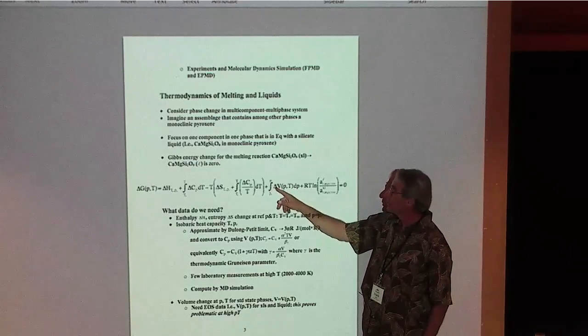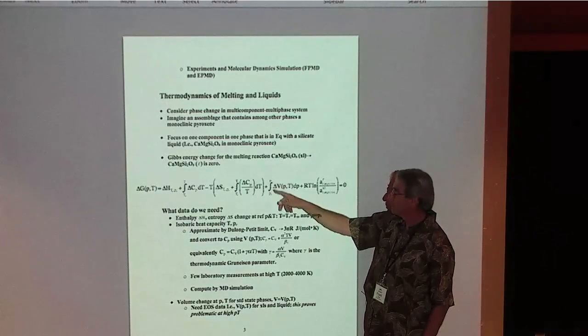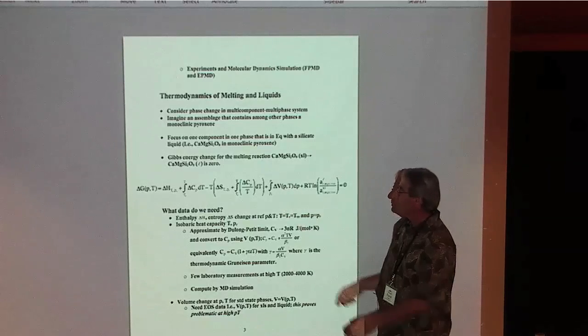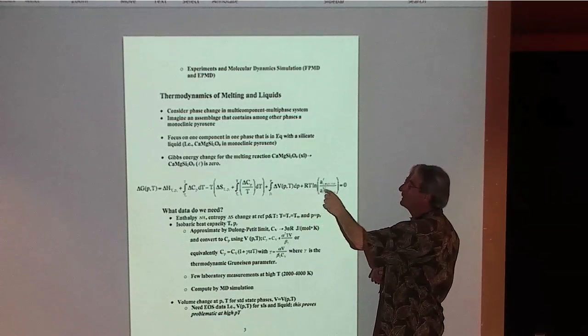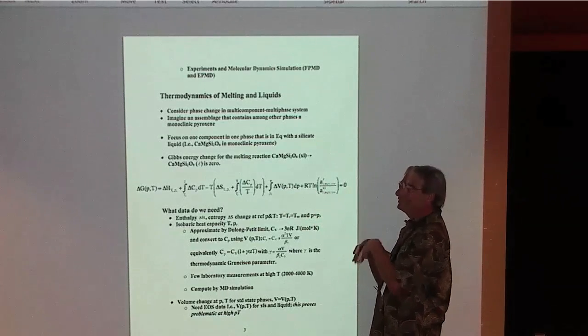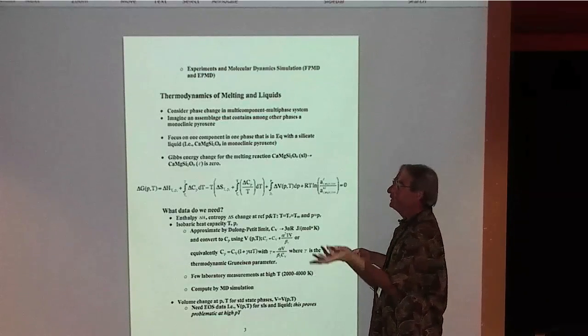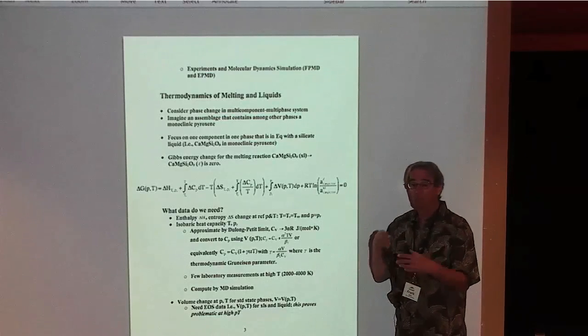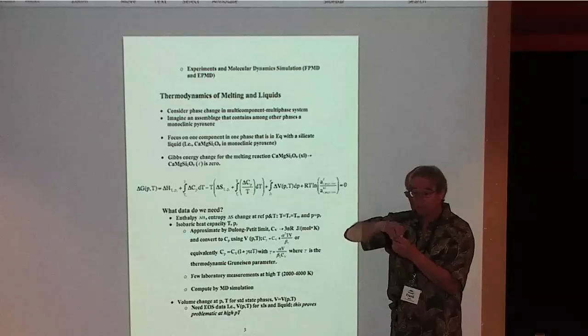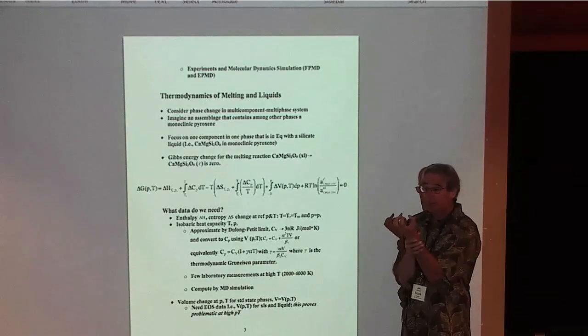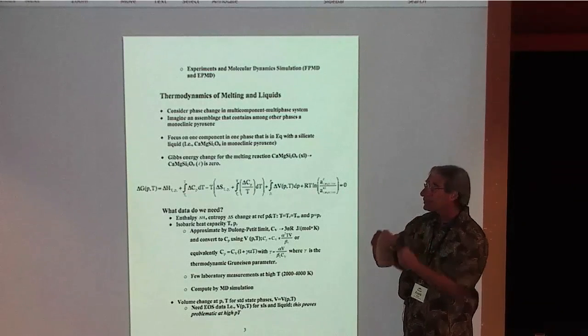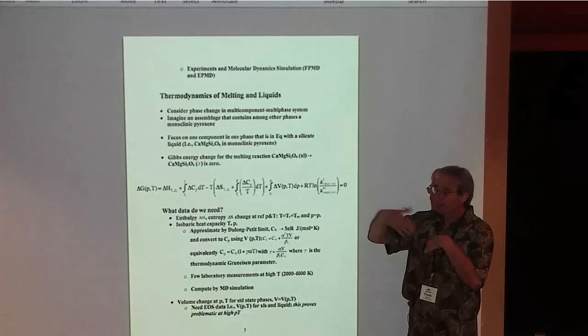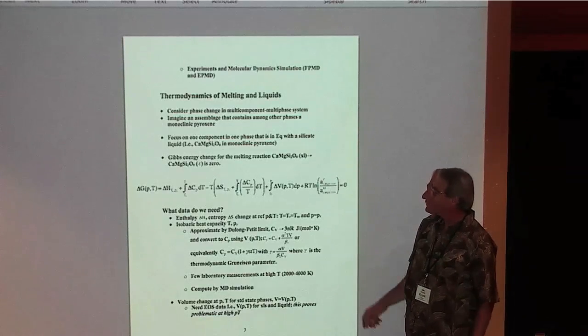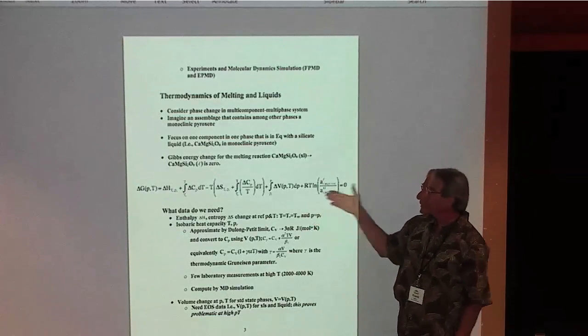And notice this is an integral over pressure, and that presents some problem. And then we account for the fact that this diopside crystal is not pure CaMgSi2O6, and the liquid's not pure CaMgSi2O6 if it's melting to form a basalt. You have crystals of pyroxene in equilibrium with this liquid. We account for all that off-composition stuff in these activity terms. At any rate, the fundamental expression is here.